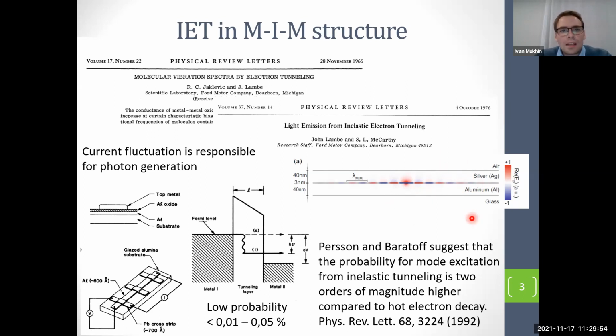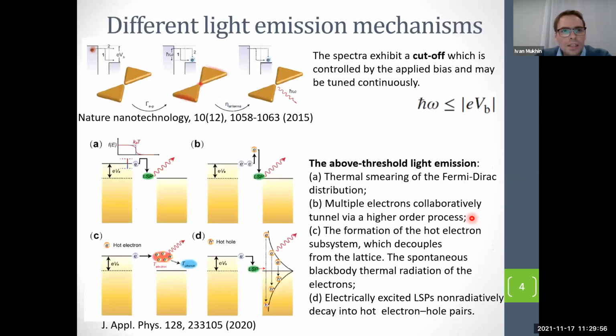Yeah, and this process was described a little bit later. So again, the energy diagram. So it could be an elastic process, number 2, and an inelastic process. During the inelastic process, or decay of energy of the elastic process, we can excite an optical plasmon mode in the tunnel gap, which can then decay radiatively and emit light.